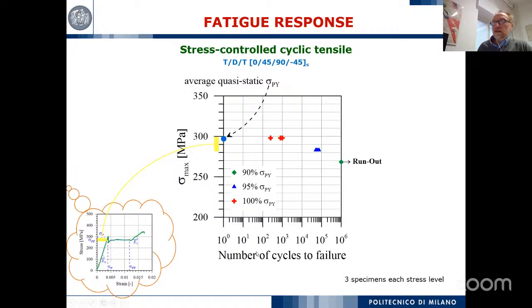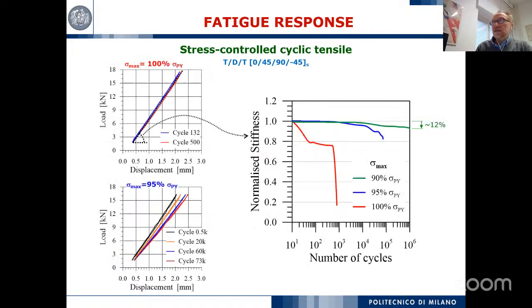The reason for this is that when we get to this level, the fragmentation starts, and then, keeping the same stress level, the material has a fast evolution of damage, and it jumps to the other branch of the static curve, and then it fails more quickly. In summary, if you look at the evolution of the stiffness of this material, or the slope of the stress in the cycle, you see that we have very good retention of stiffness if we work at 90% of the pseudo-ductile stress, but this will immediately drop down if you are very close to or at the stress of the first peak.